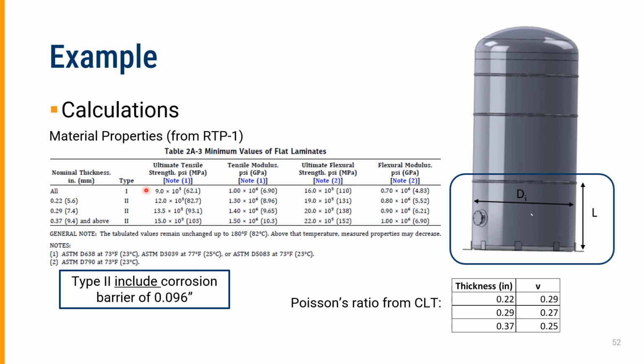And if you look down this table, you'll see that those properties are all less than the properties of any of the type 2. Type 1 has no unidirectional fibers in it. The type 2 has varying degrees of unidirectional fibers. And in fact, we have type 2 of particular thickness, and you can see that these values increase a bit as the thickness increases. Okay.